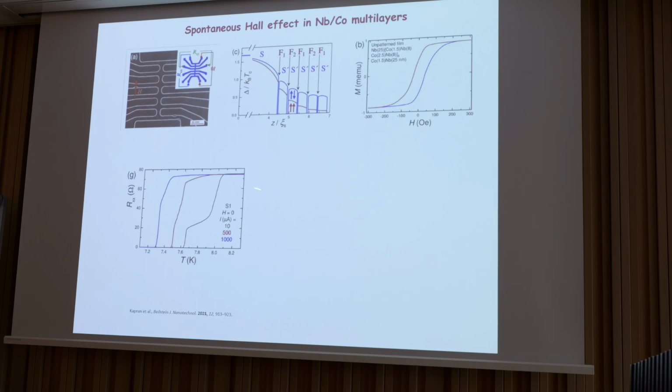And you can see that there is a remarkable shift in the transition temperature. I want to emphasize that this shift does not mean that we kill superconductivity by this tiny current. What happens is that as we increase the current, the seeming onset of the resistive transition shifts to lower temperature.